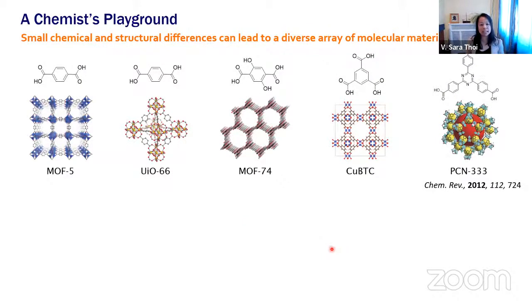Really, this type of material is kind of a playground for chemists, right? You think about how just using different metal ions with the same organic linker can lead to a variety of different structures. Here I'm showing you that the zinc ion gives you this very cubic structure, whereas if you use zirconium ions, you get these very neat polyhedrons that are formed using the same organic linkers. Add some functionality to that organic linker, you now get these pseudo two-dimensional materials, make it tritopic, and adding other functionalities gives you even more structural variability.